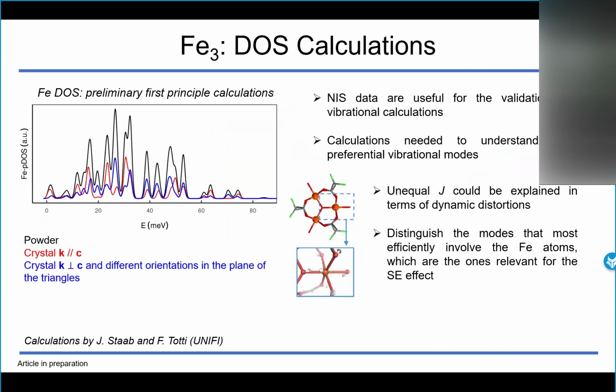And we were very satisfied by this data, which was useful for the validation of the vibrational calculations. These calculations are ongoing, so I show only some preliminary first principle calculations that confirm what we have seen in the experiment. For example, if we consider the gamma ray parallel to the z-axis or perpendicular to the z-axis, we have different peaks. And also, if we stay with the gamma ray perpendicular to the z-axis and we experiment different orientations in the plane of the triangles, then the spectrum doesn't change. These calculations will be refined, also because the focus will be to understand what the preferential vibrational modes are in these molecules.